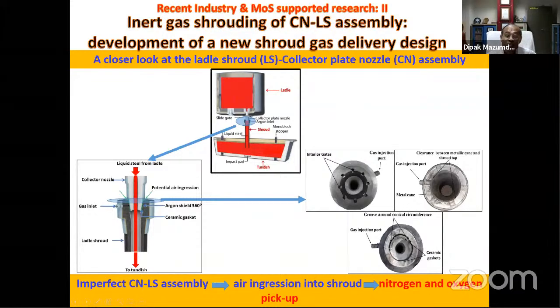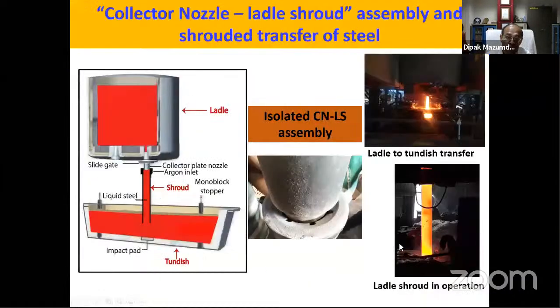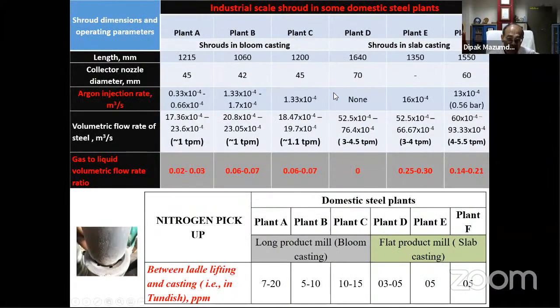And nitrogen and oxygen pickup, as we have seen in the case of the aluminum fading graph that I have illustrated earlier, is reoxidation that takes place. So this is the collector plate, collector nozzle, and this is the ladle shroud. It's an isolated one. Somebody is holding it. You don't see that person behind. So this is the nozzle through which gas is injected, and through these ports the argon comes out, and this shows the ladle shroud in operation in the steel plant. And this is a picture which indicates how molten steel from the ladle is transferred into the continuous casting mode.